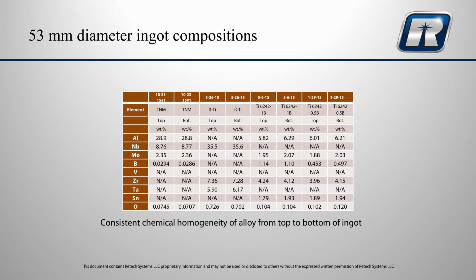We've also done some work with 6242 with boron additions at different levels, 1% boron and 0.5% boron. That was quite a challenge, but we've been able to do it. The idea here is that we have mixing not only in the hearth but in the mold, and that's what we feel is very important in the success. So what we're doing is taking on-composition compacts to start with and converting them in one melting operation to on-composition final alloy ingots. That's one of the ways we see that we can reduce the cost of production of the titanium aluminide materials, by only melting one time. There's also a potential quality control advantage.